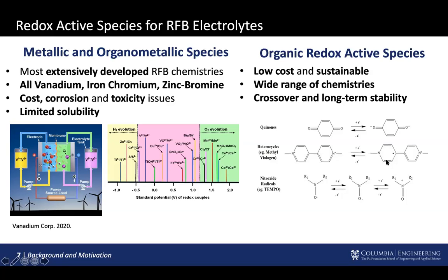But again, there's a new set of issues that have appeared in this field related to them. One of them is the crossover. I described what that is previously, but essentially these small organic molecules can easily cross over from one compartment of a battery to the other. And in order to prevent that from happening, what's currently being used is very selective ion exchange membranes. The issue with that is that those membranes are actually very costly. So even though we're using a low-cost molecule, that comes at the expense of using an expensive membrane.